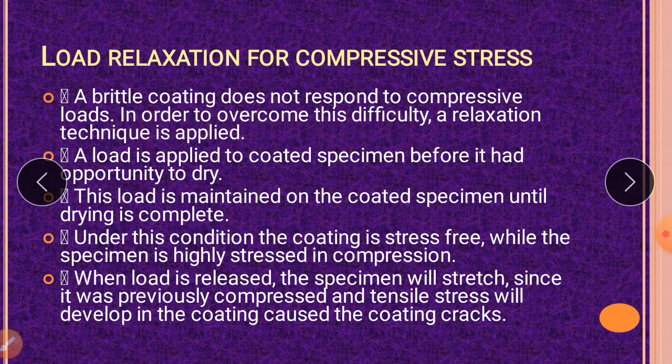In order to overcome this difficulty, a relaxation technique is applied. A load is applied to the coated specimen before the coating has an opportunity to dry. What do we do? We will consider one specimen. We will apply the coating, and in a very fast manner we apply the load. Okay, before the curing, the coating is not yet dried, so in that condition only we apply the load. This load is maintained on the coated specimen until the drying is completed. So we will apply the load until the coating dries over the specimen surface.